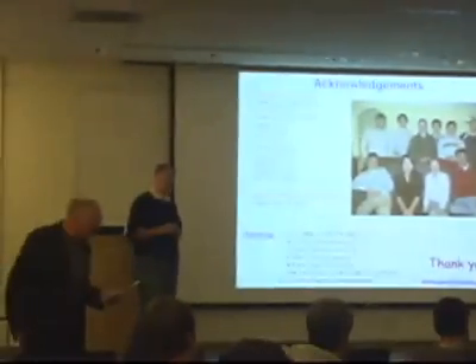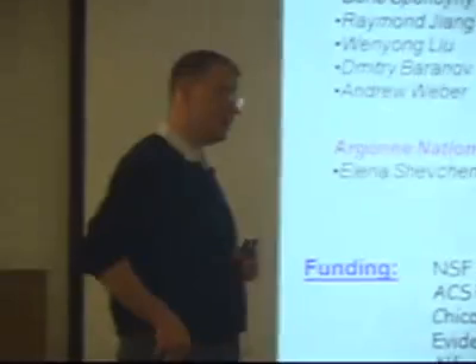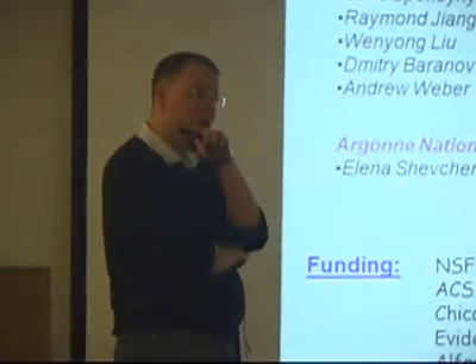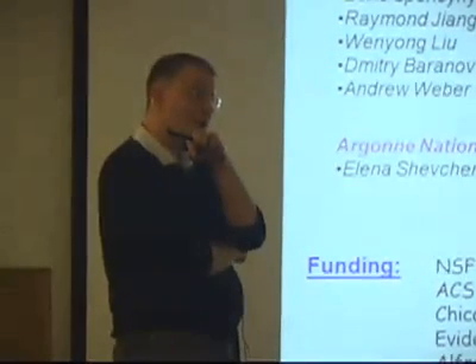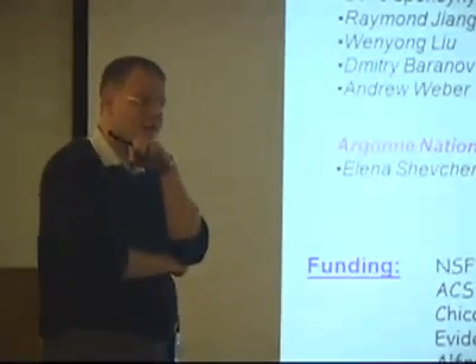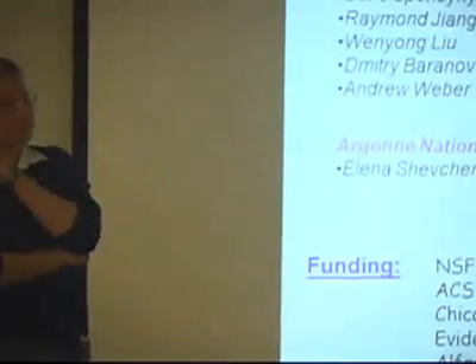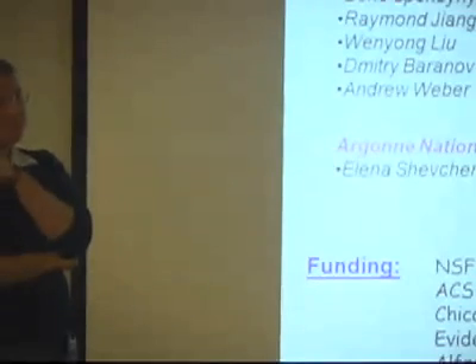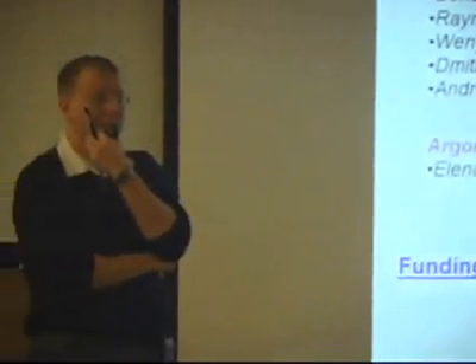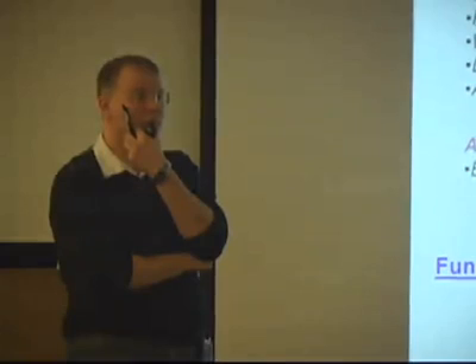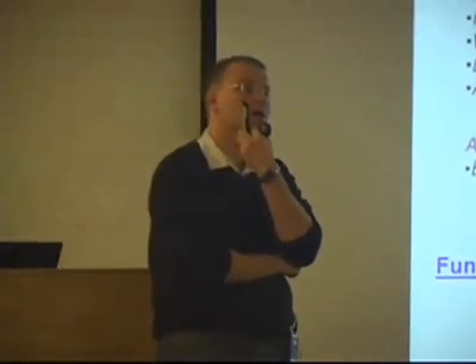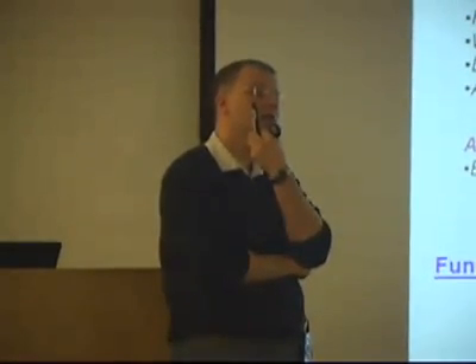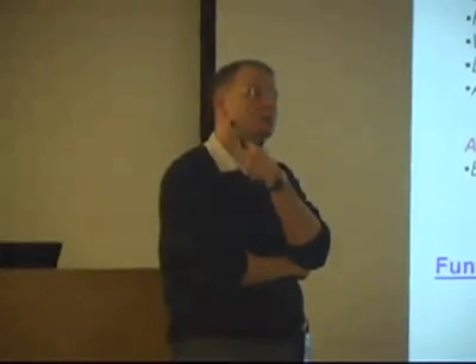The approach we have taken recently is to eliminate the ligand altogether. We use butylamine, which functions both as the solvent and as the ligand. And then with mild temperature, you drive it away, and you get really a direct contact between the nanoparticles. We demonstrated photoconductivity of such films, which is published in JACS, and the films that we make that way are pretty good, almost as good as any conductor.